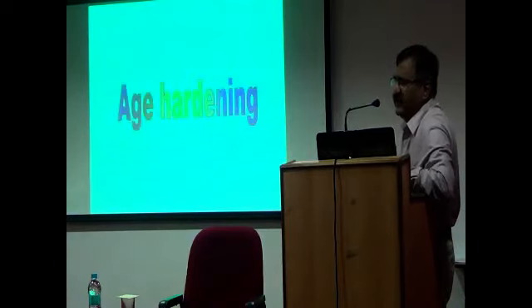Similarly, age hardening is a phenomenon people are familiar with. It's basically getting a high hardness. People know the tempering, the steel tempering, things like that. Similarly, in aluminum alloys, there is the age hardening phenomenon. Normally you need to heat treat for 8 to 10 hours, but in the case of the composite, you can do it for only 4 hours. You can achieve the required hardness.